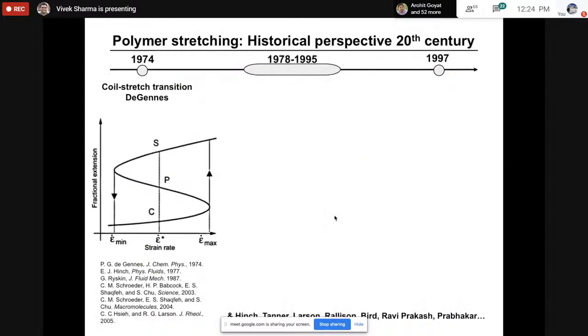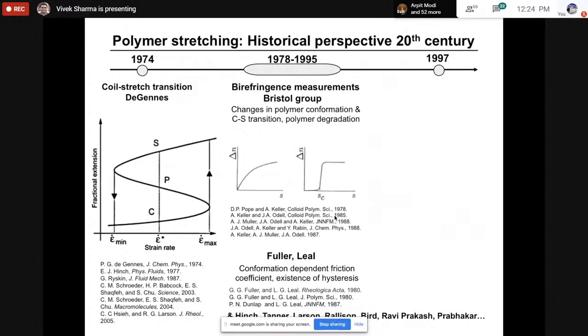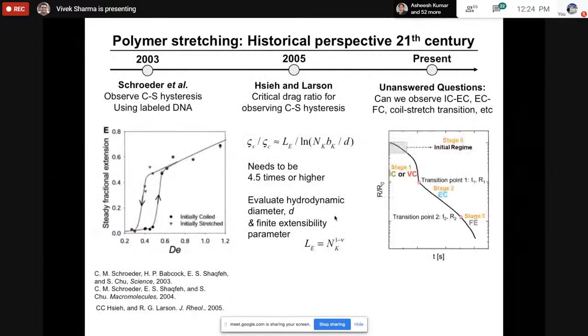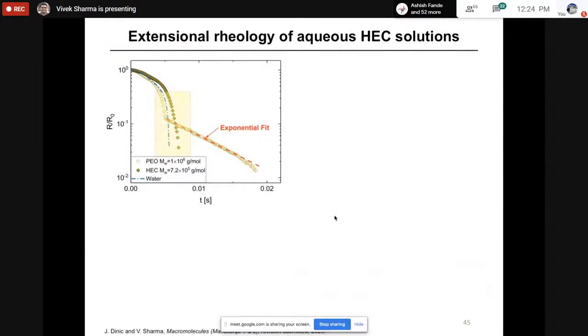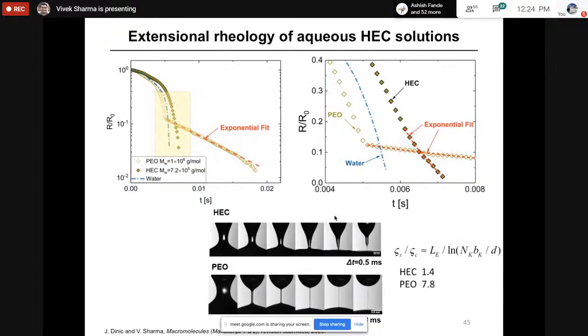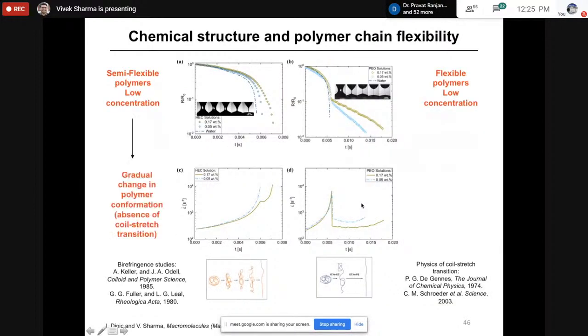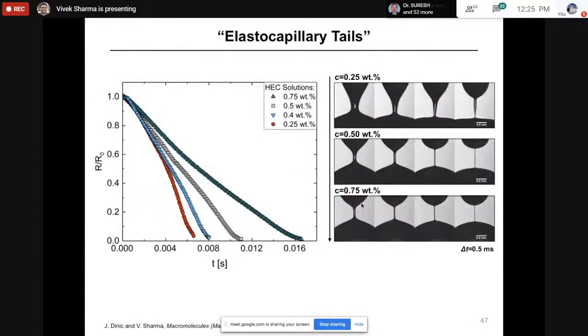And to explain this, we really had to go back and dig through understanding of coil-stretch transition and so on. So I'm going to skip through some of this. And the key idea that comes out of all of this is that we were able to quantitatively come up with a criterion that tells you why we see such a sharp transition in the radius evolution for PEO. It undergoes what is known as a coil-stretch transition. And the criterion for the coil-stretch transition depends on the friction coefficient for a fully stretched chain compared to the friction coefficient for a coil. And for something like PEO, which can stretch quite a bit, this number is large enough that we see a very pronounced elastocapillary regime. Some of this was published only recently, and you can avail of those in these Macromolecules papers that just came out.